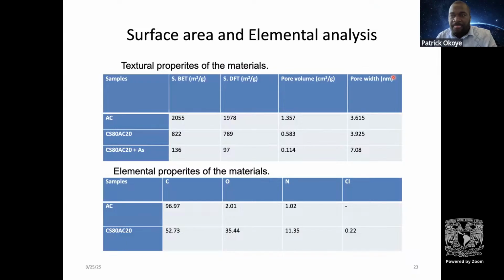So the textural characteristics of this material show that we have over 2,055 square meters per gram. This shows obviously that if you use about 5 grams of our material, you will have about a standard football field. And then the best material, which is 80% chitosan and 20% activated carbon, has a surface area that is even far lower, and even worse when the arsenic was put.